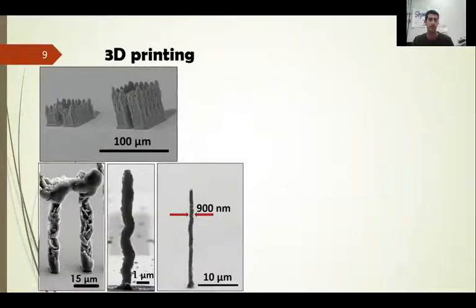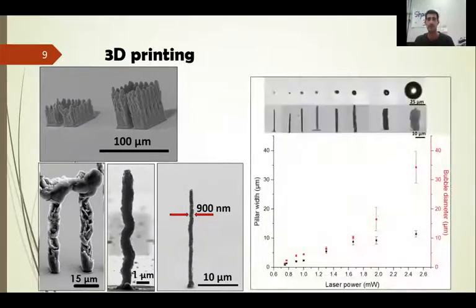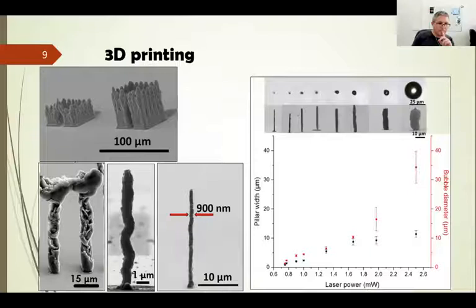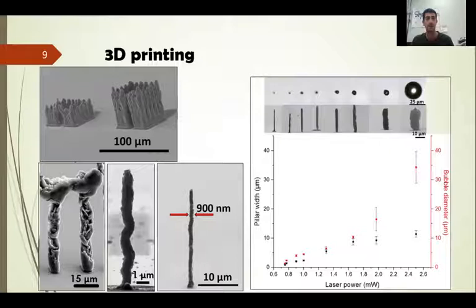We can see here some bridge, spring, castle, and we can see also that we made some pillar with resolution of 900 nanometers. So we succeeded to reduce the minimal feature size to less than 1 micron. Here in this graph, we can see how we control the width of our structure by changing the laser power from 900 nanometers to 10 microns.